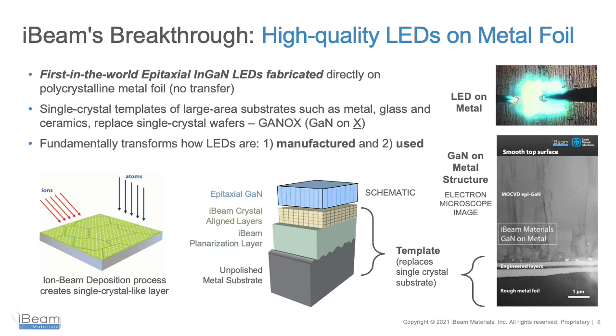We utilize inexpensive metal foils which are as rolled and still rather rough. Before depositing the ion beam aligned layer, we planarize the surface by chemical solution deposition, creating an atomically smooth surface. On the right, you see the cross-sectional electron microscopy image of what the structure looks like. And on top, you see our first LED device, and you can see the rough metal foil through the gallium nitride material. The gallium nitride and LED deposition was done by our collaborators at Sandia National Laboratory in New Mexico.